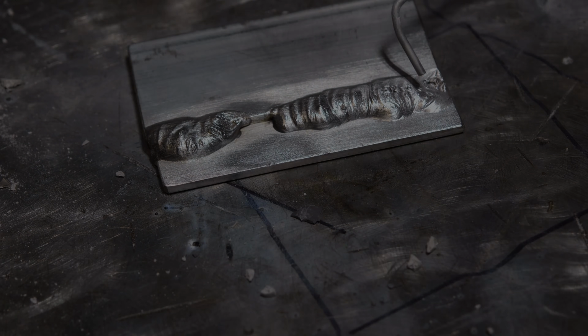Probably not. Here are two clips where I use that flux-coated rod that's meant for stick welding to weld aluminum. And you can see that it's quite a mess. It pops, it contaminates the tungsten. It's generally speaking no fun, and you can't see anything that's going on. Let's watch this in real time.